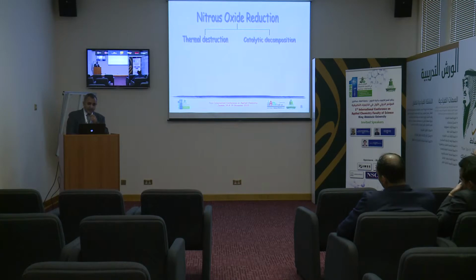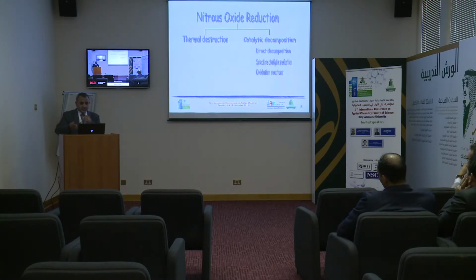Regarding the possibility of or the ways of reduction of nitrous oxide, there are two main categories. The first one is the thermal destruction. The other one is the catalytic decomposition. And the thermal destruction requires high energy, high temperature, around maybe 700 or more degrees. So it's costly. The other alternative is the catalytic decomposition, and in that category it has three subcategories. The first one is the direct decomposition, I mean to decompose N2O into its elements, nitrogen and oxygen.